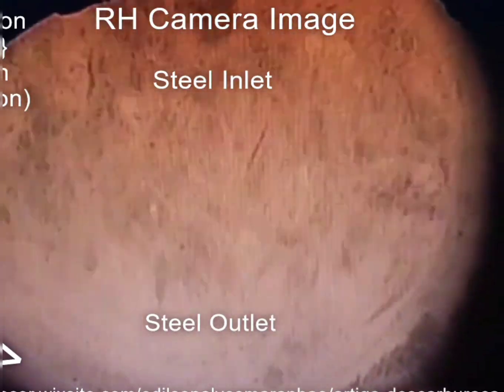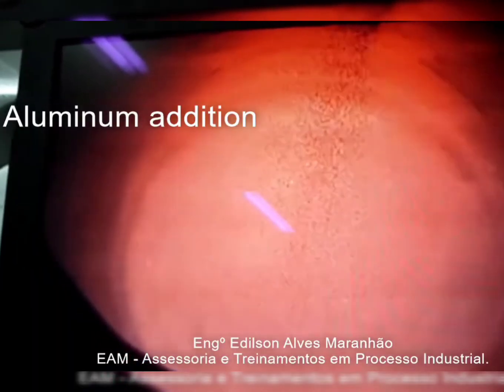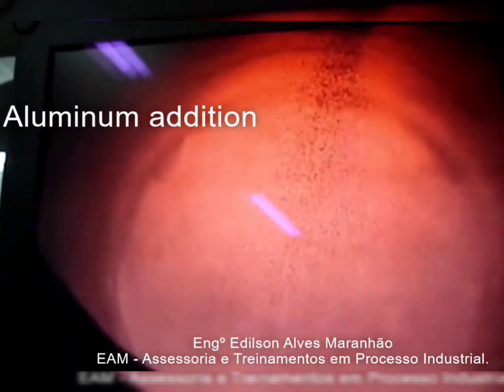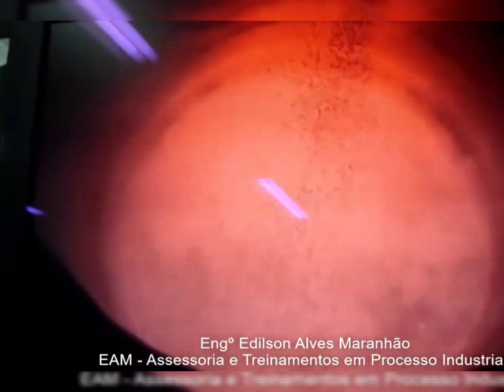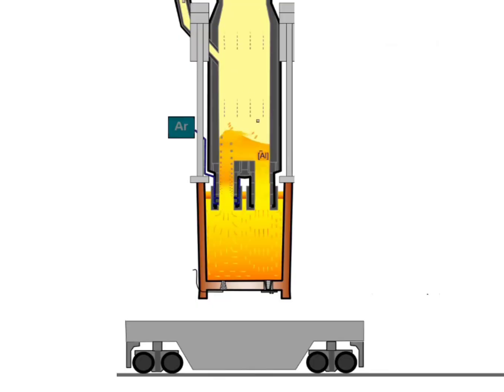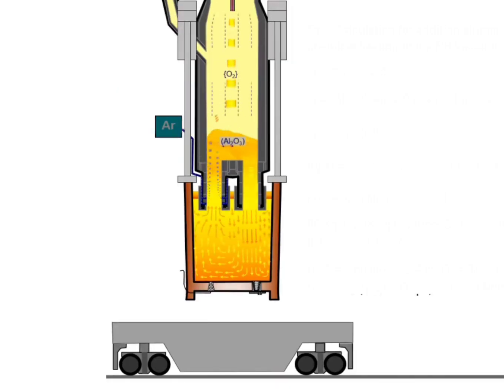The vessel is equipped with a vacuum lock through which alloys can be added without disrupting the vacuum. Alloy additions are made to enhance the steel's chemical and mechanical performance, as per the customer's specification. During the degassing process, certain grades of steel can benefit from aluminium additions. Aluminium reacts with oxygen exothermically and contributes to maintaining the ladle at a temperature suitable for subsequent casting.